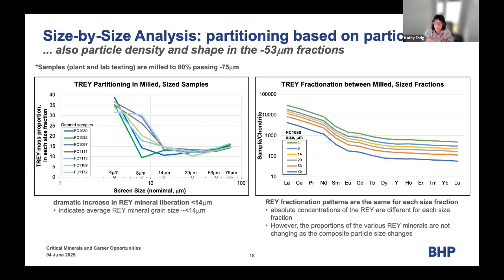Now we can also look at saying, well, are those different rare earth minerals that have a different rare earth concentration pattern? Are we somehow magically putting a specific rare earth mineral down into a fine fraction and keeping another one at a coarse fraction? What this is, is a chondrite normalized example of one of those samples that I showed on the left-hand side. And what that chondrite pattern does is just normalize it, so we don't see all the spikes that we usually see when we're going odd, even on the periodic table. And that just allows us to make a smoother transition. But what we see is there's no change in that rare earth pattern as I'm going across the different size fractions. The absolute concentration of the rare earths in it is changing, as we know that.